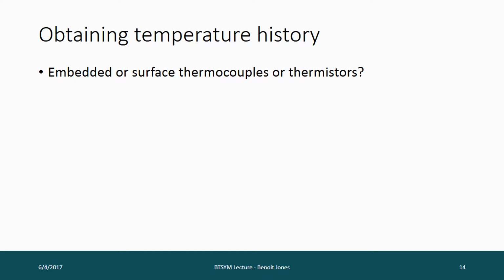So we know how to do lab tests and get these parameters so that we can say what the degree of hydration of shotcrete is based on a temperature history. But how can we get that temperature history? And like the title of the presentation gave it away, you could use thermocouples or thermistors, either embedded in the shotcrete or mounted on a surface to measure temperature. But the problem there is you have to install them. You have to go into that red zone and install them, and that's just not allowed. Also, you would be getting a very local measurement, and really what you want is to measure everywhere.